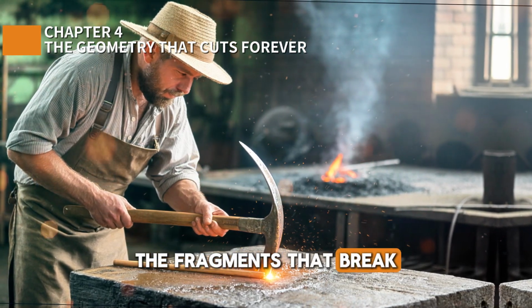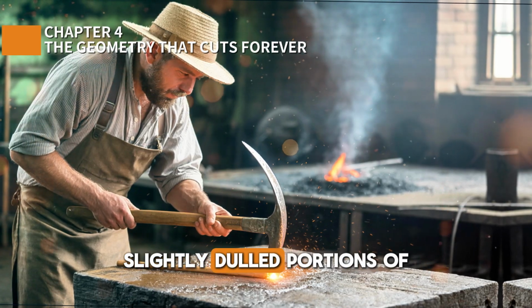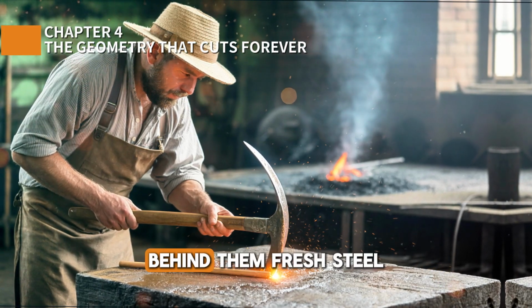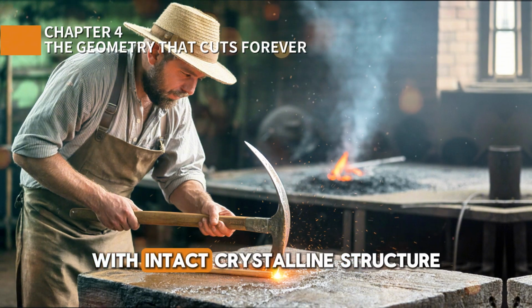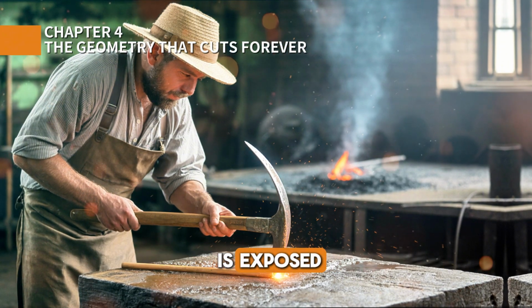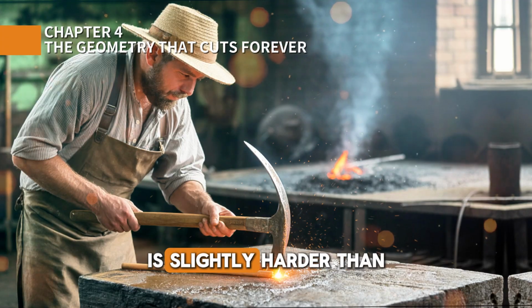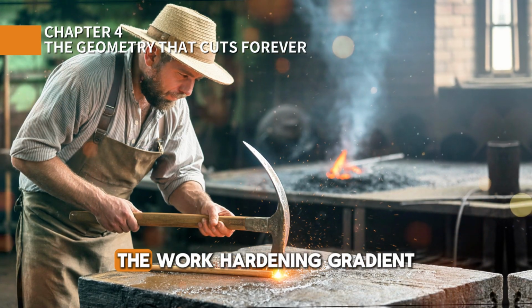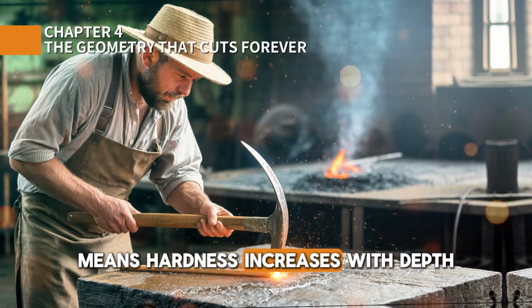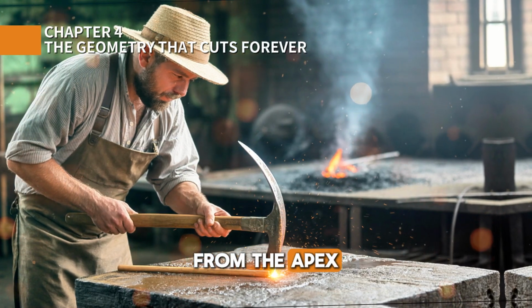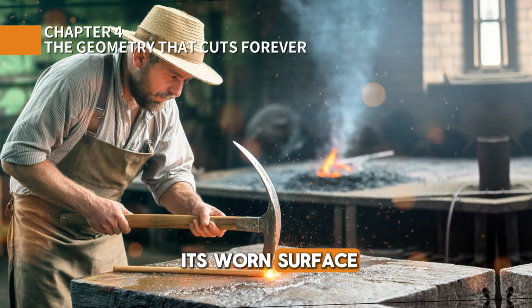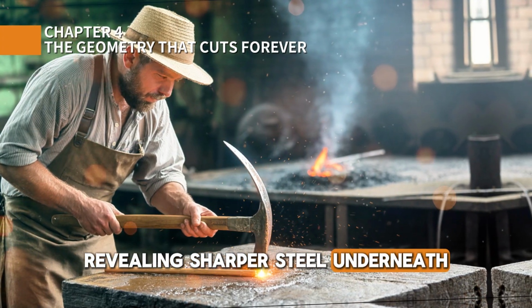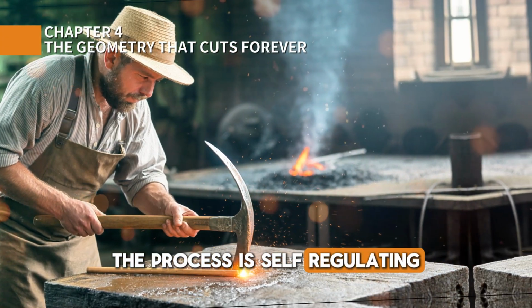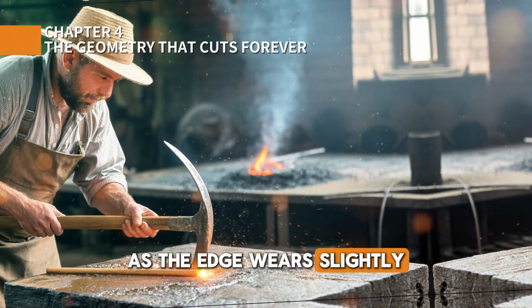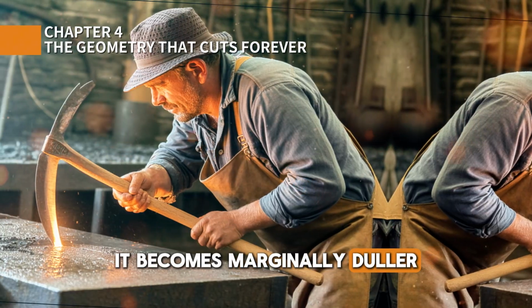The fragments that break away are the worn, slightly dulled portions of the edge. Behind them, fresh steel with intact crystalline structure is exposed. This fresh steel is slightly harder than the removed material. The work-hardening gradient means hardness increases with depth from the apex. The blade effectively sheds its worn surface, revealing sharper steel underneath. The process is self-regulating. As the edge wears slightly, it becomes marginally duller, increasing cutting resistance.